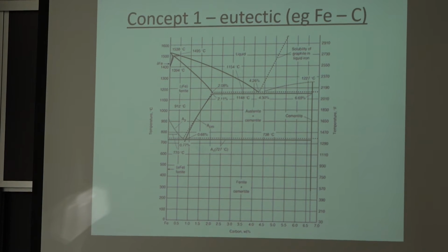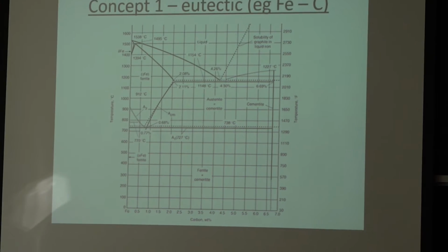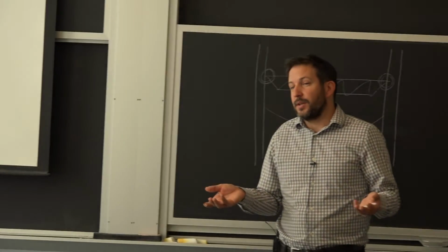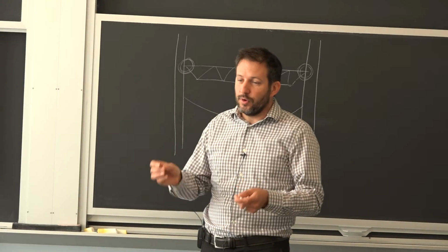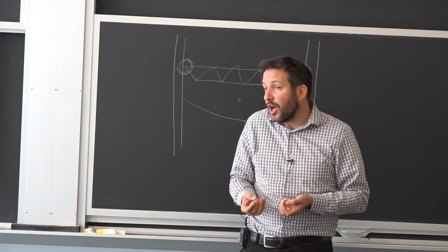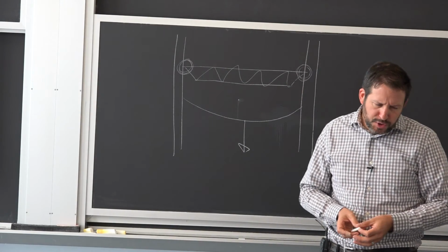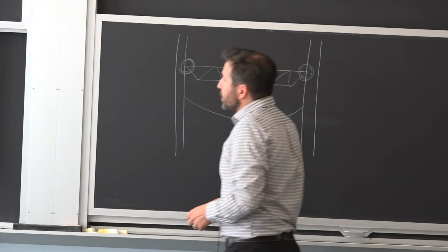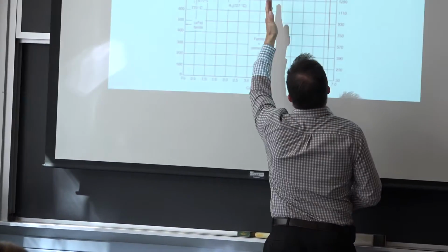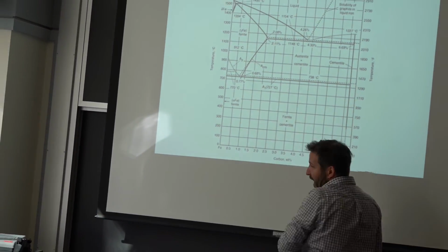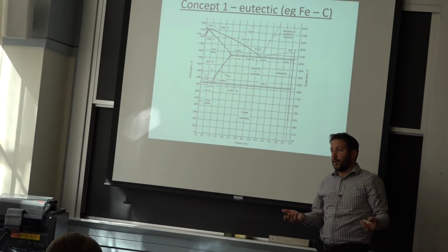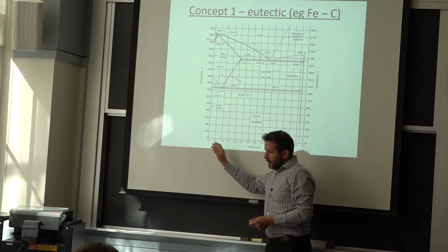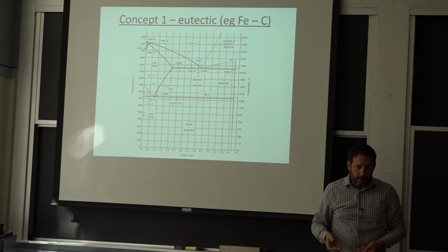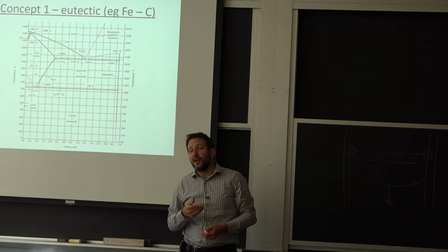And there's been growing improvement even in the past 20, 30 years, putting a little bit of this, a little bit of that. So the car frame is much lighter than it used to be because of these special developments in adding more than just carbon, a little bit of this, a little bit of that, and then you get a good combination of strength and ductility. We'll talk about some of that in heat treatment, but what I want you to keep in mind is we have these two zones. One here goes from the liquid to the solid, and that's about it. You go through these processes to try to not have a big lamellar structure that's brittle. If you want the real high strength in a wrought product, you will cast the steel and then go through a lot of thermomechanical treatment.